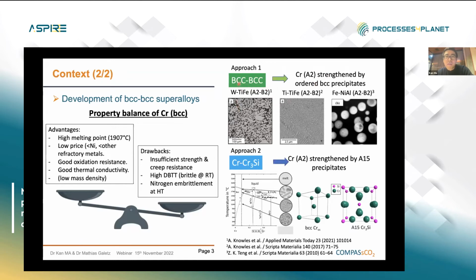And in fact, this forms so-called BCC superalloy. This concept has been adopted in other BCC metals like tungsten, beta titanium, and also BCC iron, and they achieve quite an improvement in this material. And the second approach is to introduce the A15 phase, chromium-3 silicon, into chromium to pursue both strengthening and also improve the oxidation resistance and